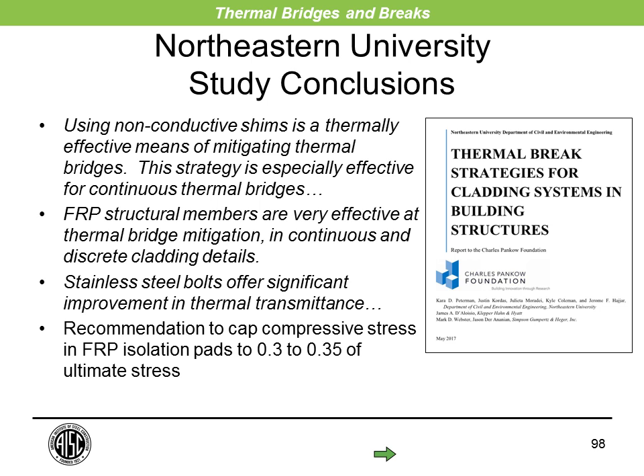I'll summarize quickly some conclusions from the Northeastern study. They summarized that using non-conductive shims is a thermally effective means of mitigating the thermal bridges. That's because the non-conductive shims effectively provide isolation between the two steel components. They also found that FRP, in other words, fiber-reinforced plastic structural members, are very effective at thermal bridge mitigation, in continuous as well as discrete cladding connections. And they also used steel shelf angles with 3x4 shims installed at bolt locations to provide discrete cladding separation in the cladding backup system. They found a significant reduction in the area of steel in direct contact with the pour stop helped. So in other words, putting shims between a shelf angle and a pour stop really helped.